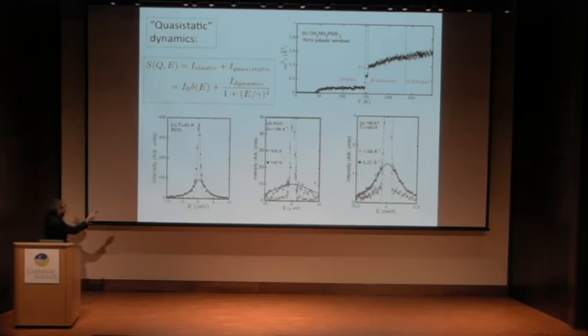So all I've done is fit the spectrometer resolution with a delta function, and then something involving a Lorentzian, basically to extract an energy width associated with this broad component that's dynamic. Okay, so that's at 50 Kelvin.